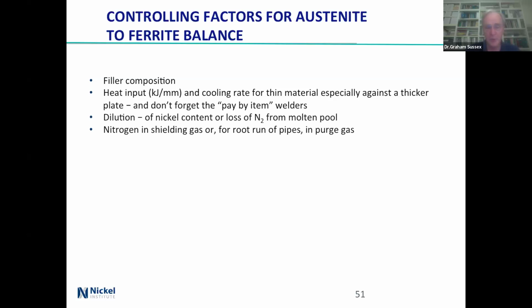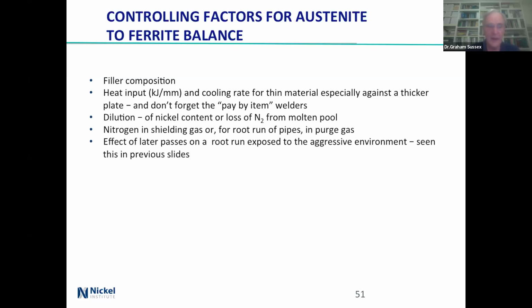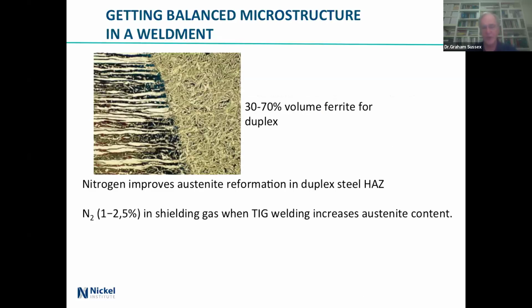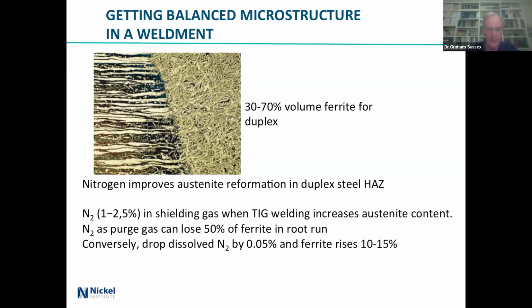Nitrogen, the shielding gas, put nitrogen in the purge gas. And effectively root passes, the later passes on the root run shown in the previous slides. Nitrogen's improving the austenite reformation in duplex steel. That's almost a tautology. You're aiming for 30 to 70% volume ferrite, but you really want it nearer to 50-50. And shielding gas, 1 to 2.5 when you're TIG welding. Purge gas, you can lose 50% of the ferrite in the root run. That's not all that good. And conversely, drop it down by 0.05 and the ferrite will go up by 10 to 15%. So it's actually a fairly delicate balancing act, and you actually need to think about it.